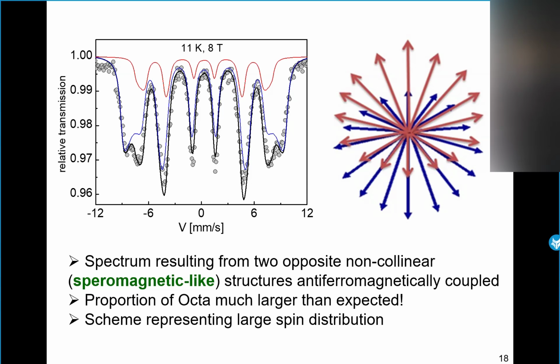Now, we also have interesting information from here. The proportion of octahedral sites is much larger than expected in the case of bulk iron oxide. It was observed that there was some tendency of the surface to be occupied by more octahedral sites than tetrahedral sites, but it is not possible to prove that directly from experimental measurement. Now, for this system formed just from the surface, we have done the experimental proof of that. The fitting model works well.